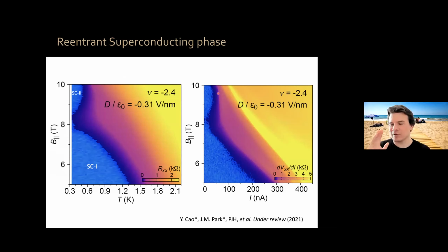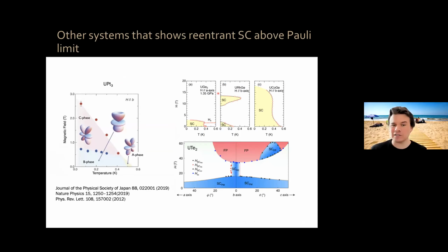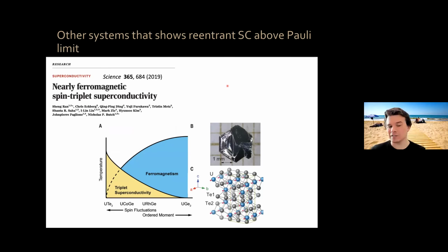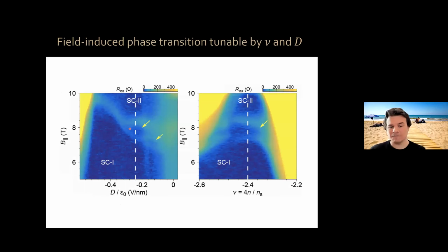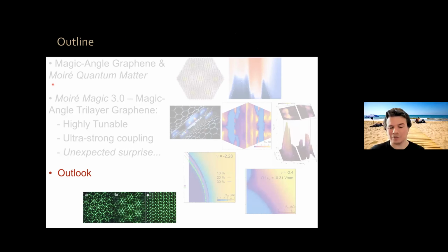It is very rare for superconductivity to reappear at high fields. There are a few systems where this happens, and these are typically ferromagnetic superconductors or spin triplet superconductors. We don't have ferromagnetism in our system that we have been able to detect in the region where superconductivity is. So the most likely option is that our system has spin triplet superconductivity. We can check the phase boundaries between the superconducting 1 and superconducting 2 regions, and this occurs over extended regions in displacement field and density. And right now, the only possibility that we and our theory colleagues have thought of is that this is spin triplet superconductivity.